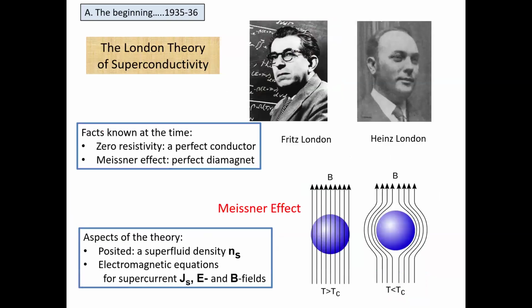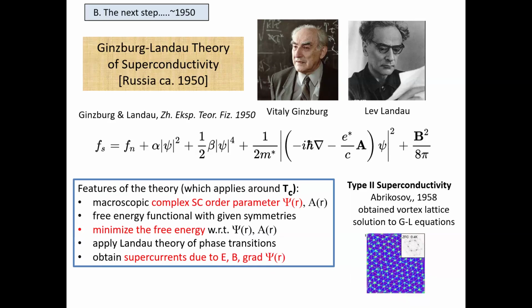And this is what gives rise to the magnetic field, called the magnetic vector potential, but it gives rise to the magnetic field B. And this describes the interaction between the magnetic field and the superconducting wave function. And that was a big breakthrough. There are 2 types of superconductors. The first type of superconductor just excludes the magnetic field until the field gets too strong, and then it just loses superconductivity. Type 2 is a different kind, and it's the most important because it's higher temperature superconductors.